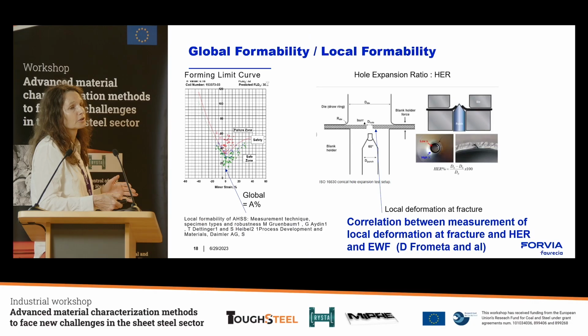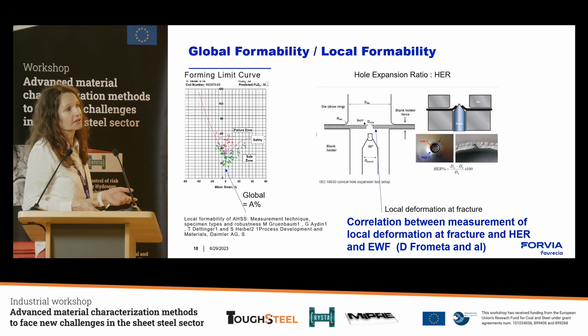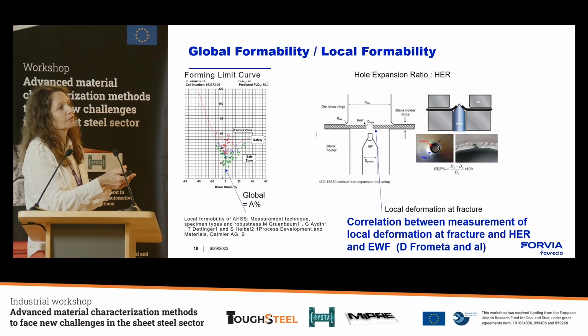It's important for deep drawing, but for fine blanking, and of course, if you are doing a hole, it's not correlated. That's why we have this hole expansion ratio currently in-house. It gives important and also consistent data regarding this behavior, but it's not easy to set up this type of test, because there is a dependence on the machining of the hole, and you have a result which is not really material intrinsic.